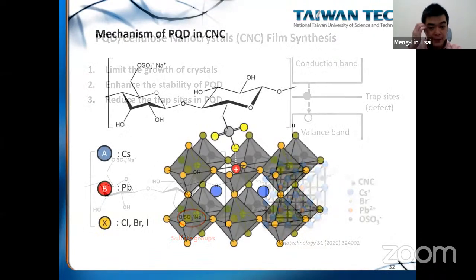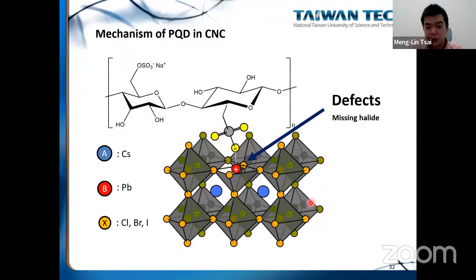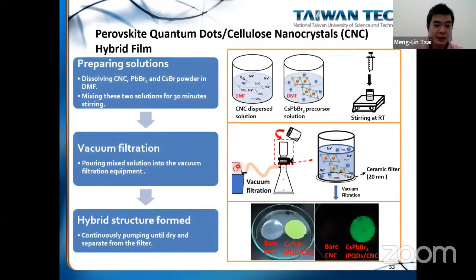Okay, and this is actually a schematic to show that it can be used to replace the missing halide to further stabilize the structure. Okay, and this is the preparation method. We first prepare a CNC cellulose nanocrystal dispersed solution and also the precursor solution, and we mixed it. We stirred at room temperature, and we use a vacuum filtration method. Okay, so that the perovskite quantum dot with cellulose nanocrystal film will form on the filter.